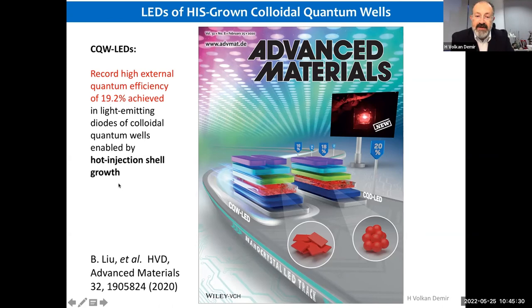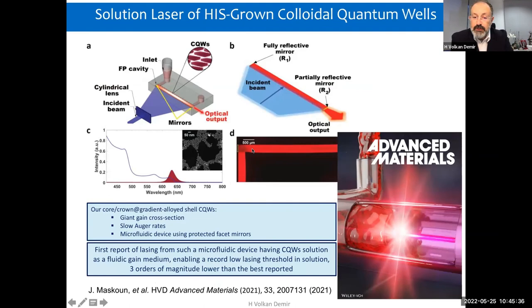Or the same material system we can incorporate into a microfluidic channel, which has its own Fabry-Perot optical cavity using two parallel optical mirrors defined on the facets of the chip. And this type of in-solution laser enabled us to reduce the threshold three orders of magnitude. So this is basically three orders of magnitude better than any other in-solution laser reported to date. So these are quite recent developments, and one can go further to engineer these materials.